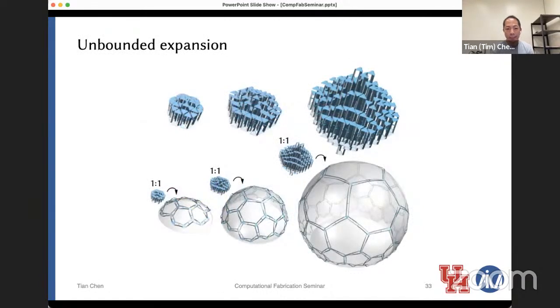And as I said before, the expansion is theoretically unbounded because we can have heights as big as we want. One demonstration of this is to cover more than a hemisphere. You can see in this case, we're able to cover almost 3/4 of a total sphere by having a uniform expansion of around 28 times around the apex of the sphere. Of course, the height cannot go to infinity in real life, so we cannot actually have a full sphere, but we can approach that much more rapidly than what we did before.